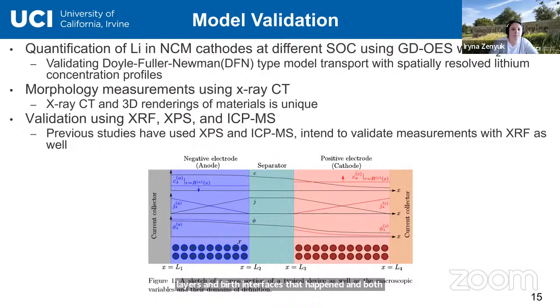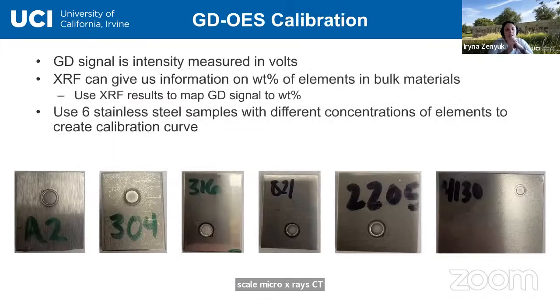In terms of calibration, it's interesting because, of course, there are a lot of calibration samples one can purchase. Those are usually very expensive, and so we came up with neat alternative ways using different stainless steels that are available, and they have different content of iron, molybdenum, nickel, and cobalt, and those are the elements that are much needed to calibrate this instrument for the cathode materials of lithium-ion batteries. And using XRF, we can get a weight percent of elements in bulk material, and we can also use ICP-MS to get more in-depth calibration.